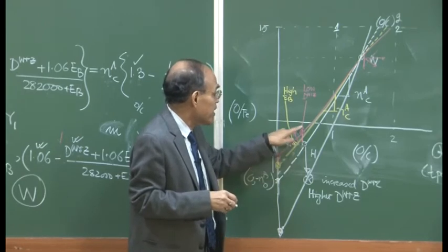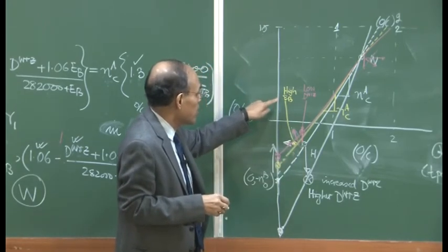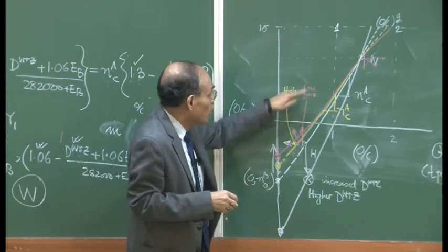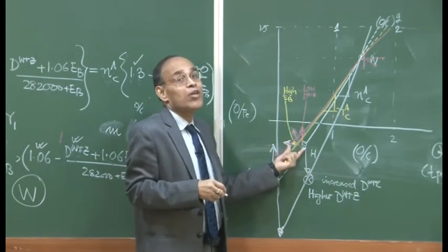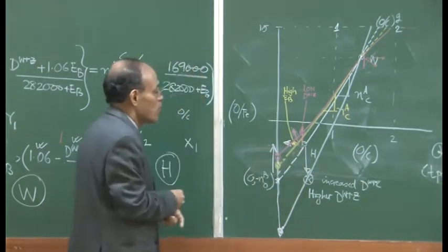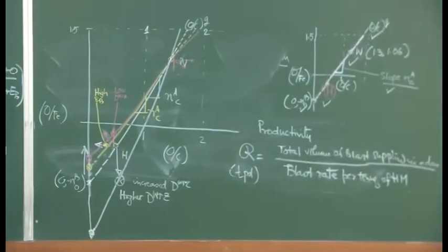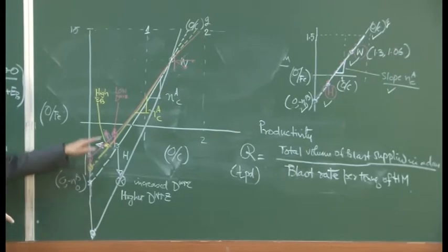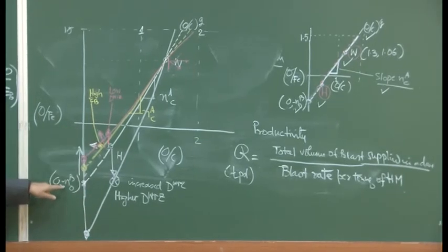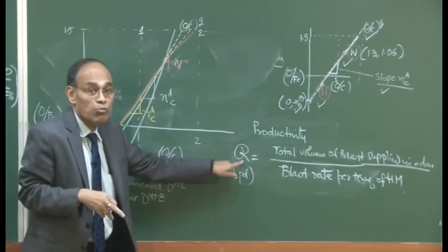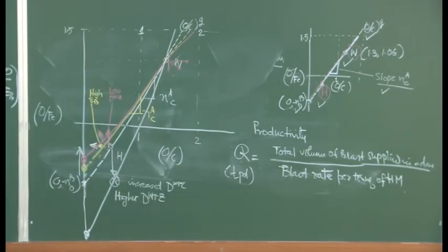As I have indicated, a higher blast temperature and a low dWRZ are required in order to improve the blast furnace operation, and we can visualize this immediately in our expression of productivity: these two cases will lead to a reduction in the blast rate, which manifests in an increase in production.